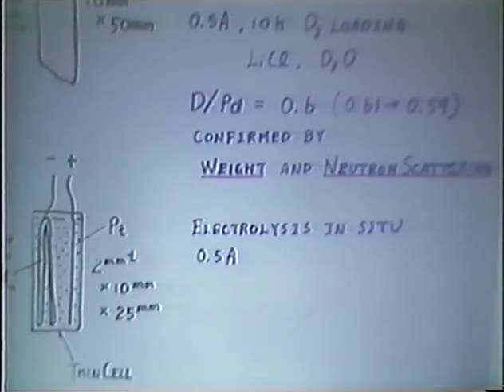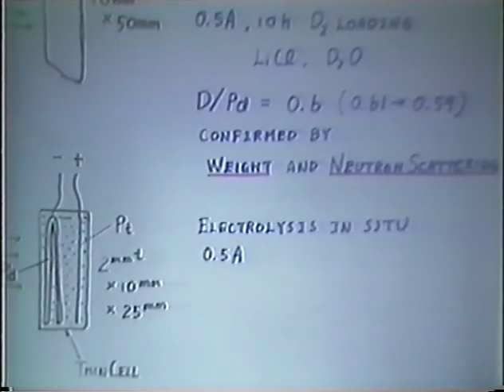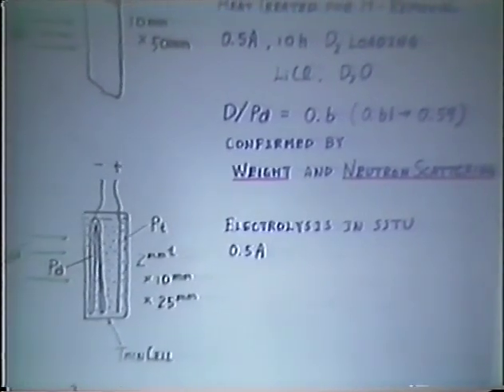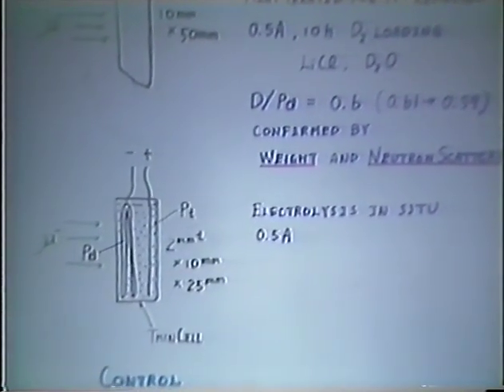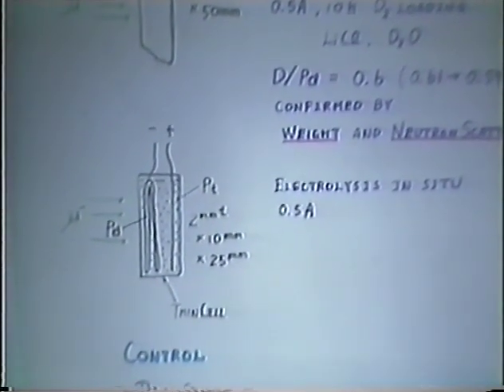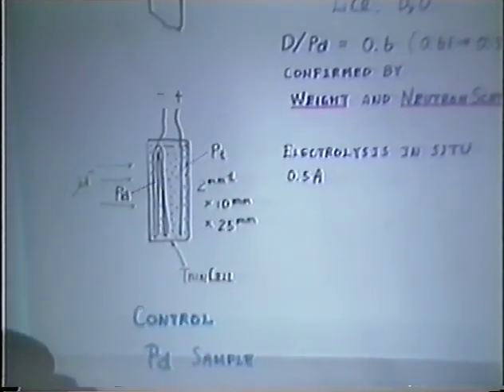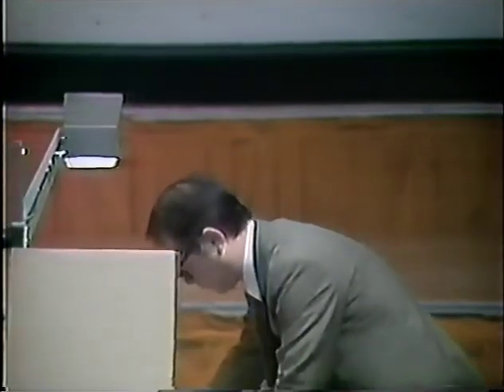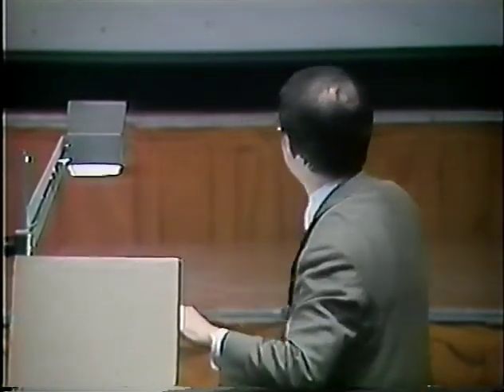And at the same time, we installed a small electrolysis electrochemical cell into our target area, exposed to the muon beam in this geometry. As a control, we adopted a palladium sample without any deuterium. This is a picture of the target area when we used the small electrochemical cell exposed to the muon beam.